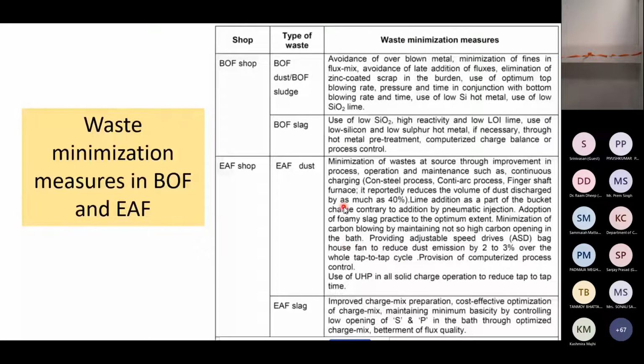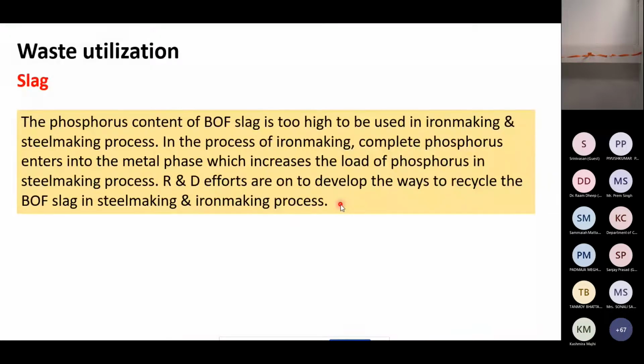Now, when we are talking about waste utilization, the first and foremost is the slag. The phosphorus content of this BOF slag is too high to be used in iron making and steel making processes. This basic oxygen furnace slag contains a high quantity of phosphorus. In the process of iron making, the complete phosphorus enters the metal phase, which increases the load of phosphorus in the steel making process. So research and development supports developing ways to recycle the BOF slag in steel making and iron making by reducing the phosphorus.